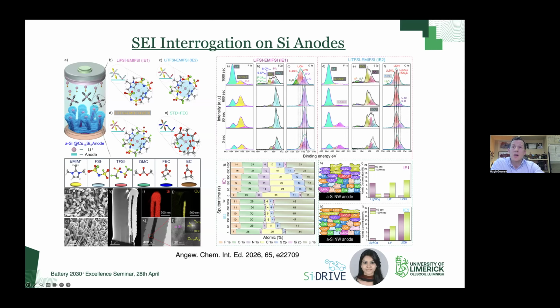And what Abhinaya did here is she used these core shell type nanowire kind of model system. So this dark core that I'm showing down here at the bottom, this is a copper silicide nanowire that we're able to grow nicely within the lab. And then these had amorphous silicon deposited on top of those. Okay, so these again are a nice high surface area model system for us to analyze the SEI composition as a function of the electrolyte composition. So what Abhinaya did was she performed XPS analysis then with depth profiling and basically was able to link the chemistry of the SEI to the decomposition pathways of the different electrolytes that were shown.